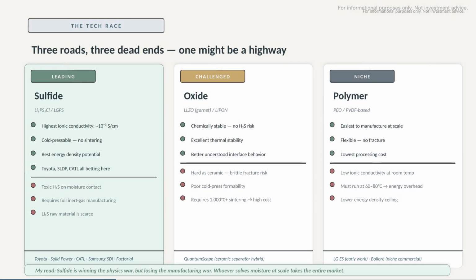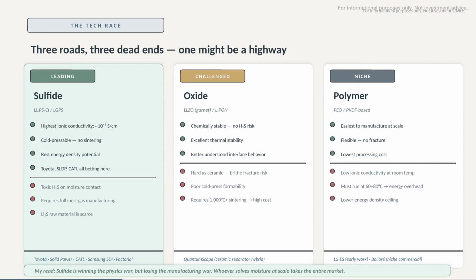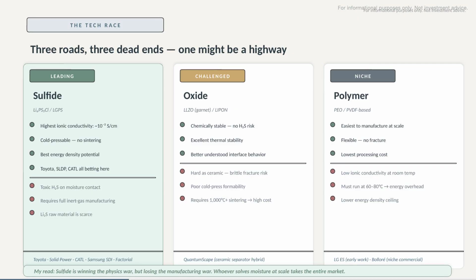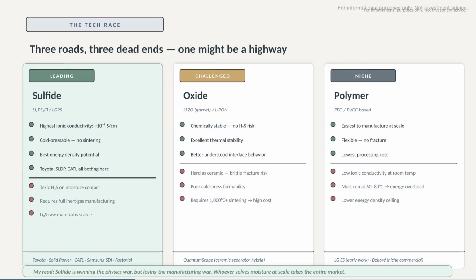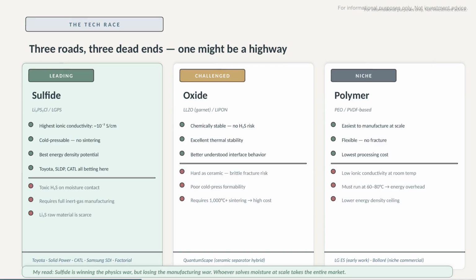3 chemistries, 3 bets. Sulfide, Toyota, Solid Power, CATL, has the best physics. Highest ionic conductivity, cold-pressable. The catch, moisture kills it, and the raw material barely exists at industrial scale. Oxide, QuantumScape's bet, is chemically stable. But it's ceramic. Brittle. Requires sintering above 1000 degrees Celsius. Polymer, LG's early work, is the easiest to manufacture. But conductivity requires 60 to 80 degree operating temperatures, and energy density ceilings are lower.